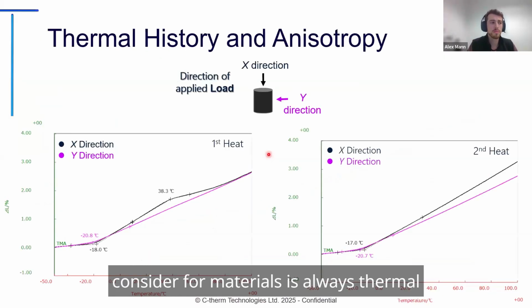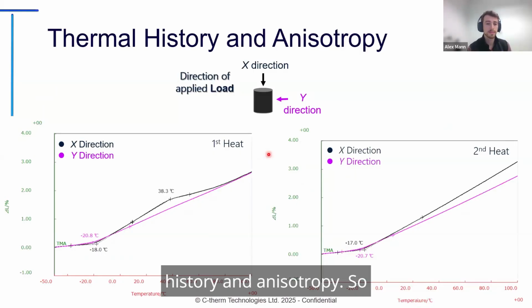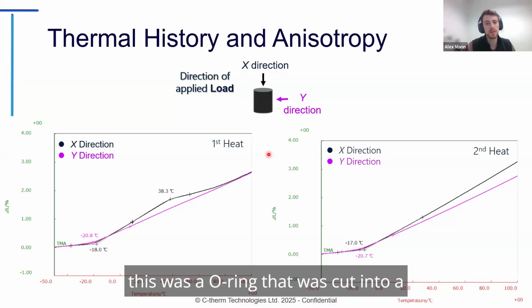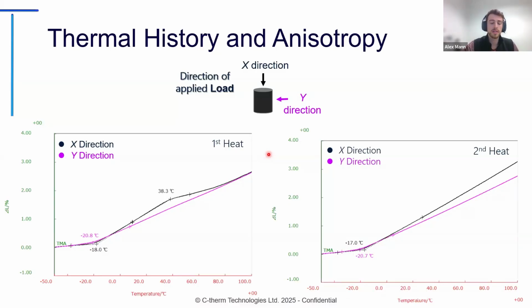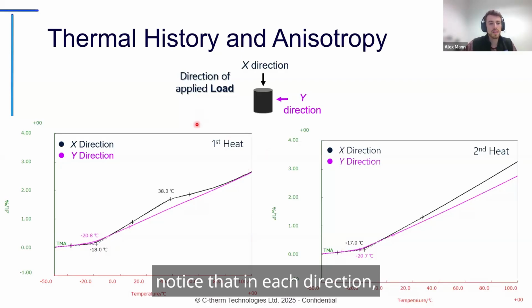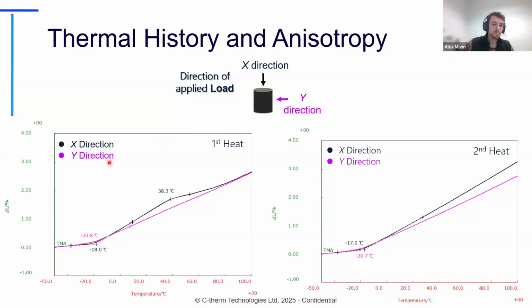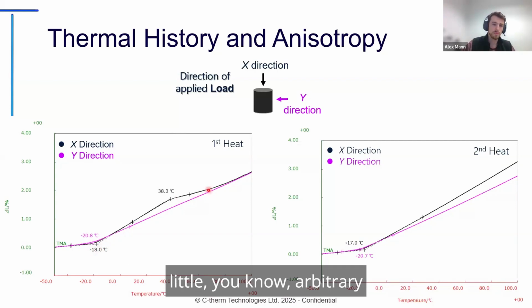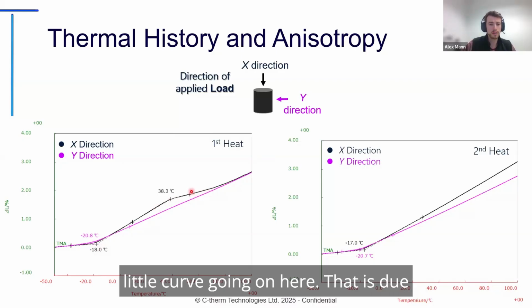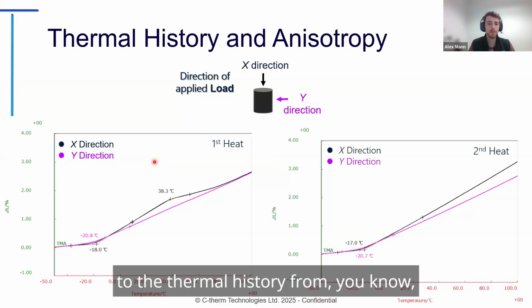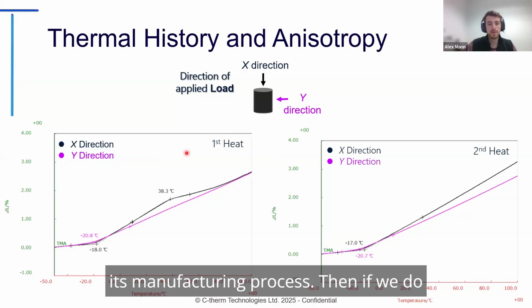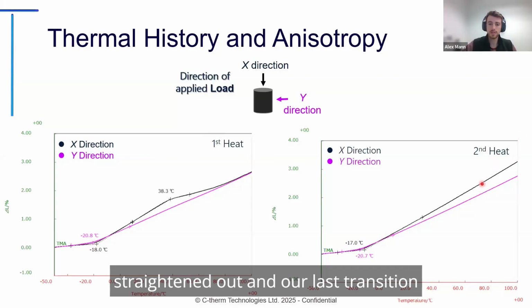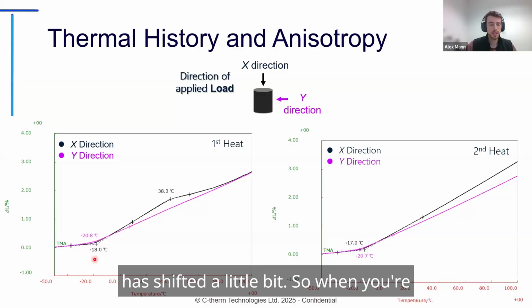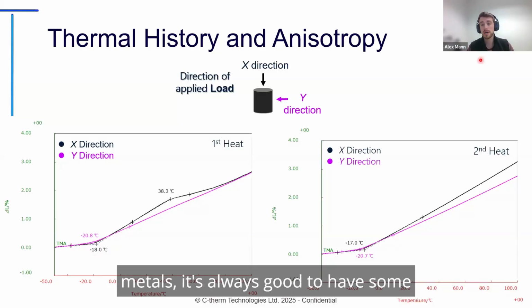Now, something to consider for materials is always thermal history and anisotropy. So this was an O-ring that was cut into a little cylinder, if you would. You notice that in each direction, there's a different expansion and different glass transition. So on the first heating in the X direction, we had a little arbitrary curve going on here. That is due to the thermal history from its manufacturing process. Then if we do a second heat, you can see it is now straightened out and our glass transition has shifted a little bit.